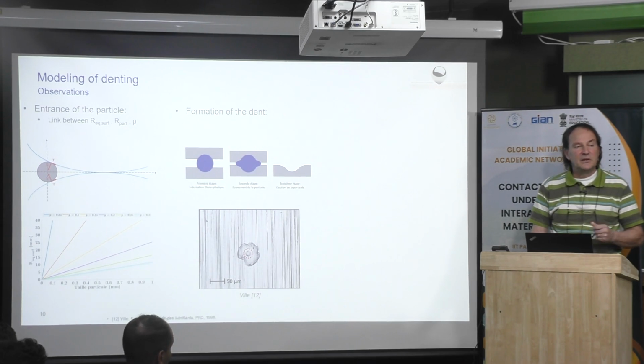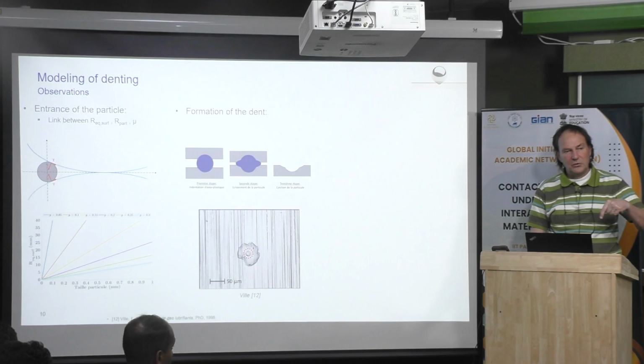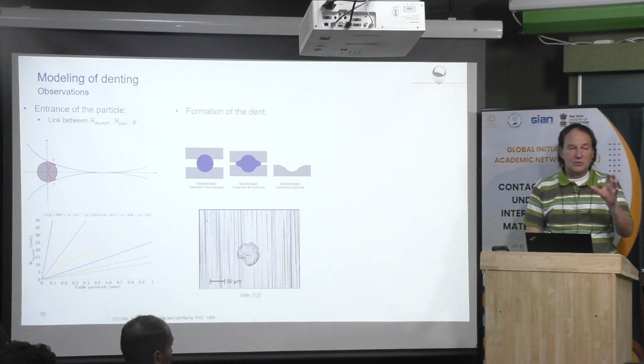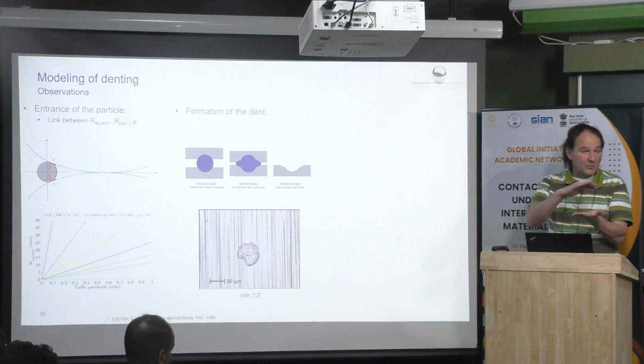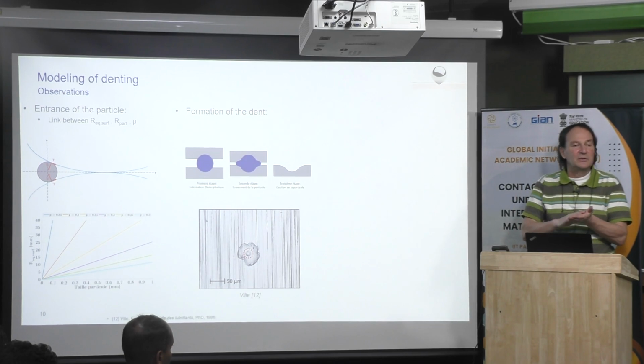Yes, yes. In fact, it depends on the number of particles you have in the oil. If you know the oil flow, you can say to have one dent, I should operate during 30 seconds. And if you have two dents, 1 minute, and so on. And plus or minus 10%, you have something like that. Yeah. The most difficult point is to have exactly the size of the particle you want to have, because you have to sieve them by class, and it should be between, for example, here it's between 30 and 42 micrometers. But okay.